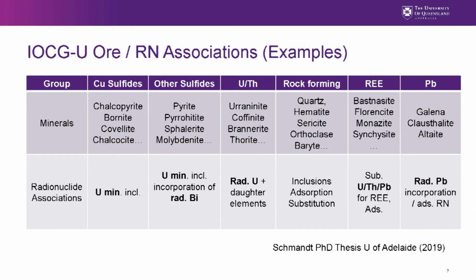And then below are some examples of where the radionuclides, or how they're incorporated into these different classes. Again, it's not extensive, but it's some of the potentially more important associations. So there's uranium mineral inclusions, which is quite substantial, and then there's incorporation of radioactive bismuth, the daughter elements of uranium, and they can move around throughout the different mineral classifications: inclusion, adsorption, substitution throughout, and inclusion of radioactive lead into non-radioactive lead minerals as well.